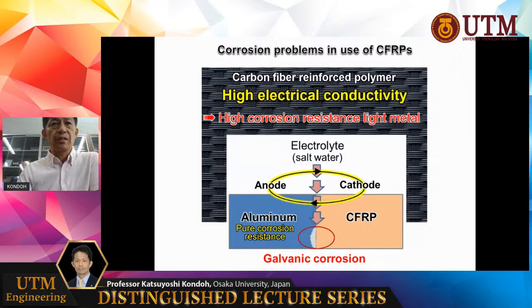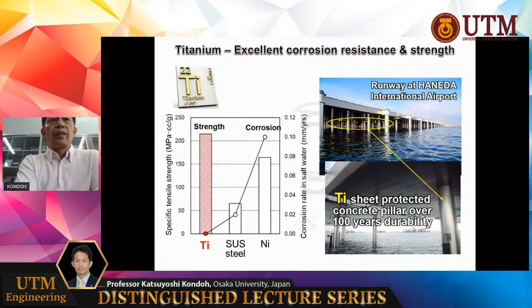Okay, in that case, we focus on titanium because titanium has very excellent corrosion resistance and high strength. Shown in this graph, this one is strength. Titanium has very high strength compared to stainless steel or nickel alloys. And this one is the corrosion rate in salt water compared to the two metals. Titanium alloys have a very low corrosion rate. That means no corrosion phenomenon in salt water for titanium materials.